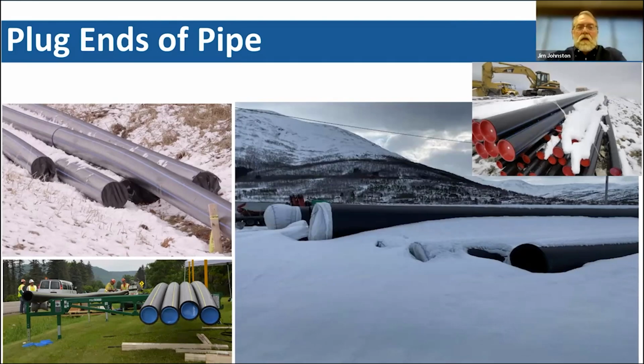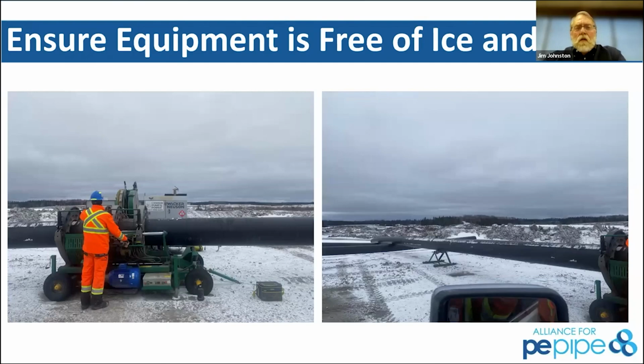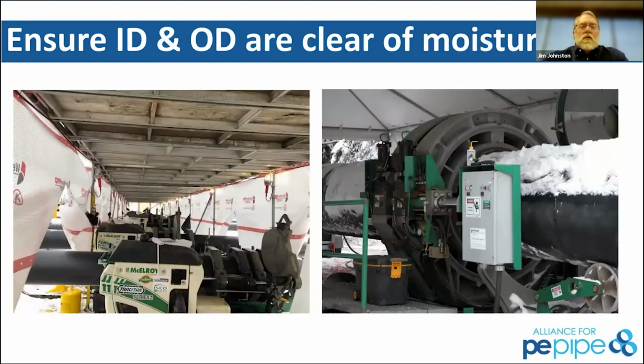So great, Richard, thank you for that. So we talked about one of the steps that are ongoing here, which is to ensure that equipment is free of ice and snow. This is also that dirt aspect. So when we talk about inclement weather, don't let snow, ice, moisture, water, or dirt get on your machine. Clean it up as much as you can, because when I finish this fusion and pull that pipe through, I'm dragging snow and ice all the way through there. Ensure that the ID and the OD of the pipe are clear of moisture. That's not just visible snow, but moisture. So you don't want that water getting into the joint, either in the ID or the OD.